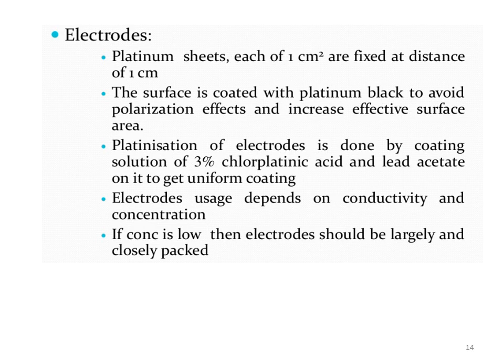We coat this 3% solution of chloroplatinic acid on the electrode, and then 3% lead acetate on it to get a uniform coating.